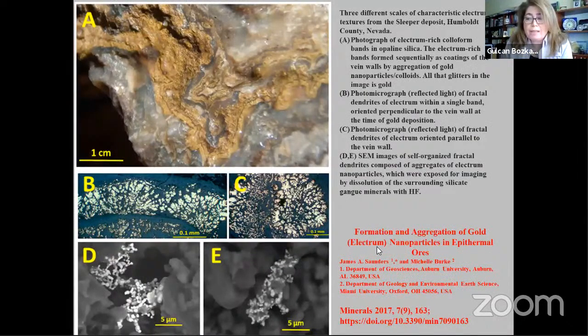It was the gold-rich bands that are present in many of the United States epithermal deposits that gave the idea of colloidal transport rather than direct precipitation from solution. Extremely gold-rich bands, as you can see, form at a variety of scales. And in the bottom two images, you can see the aggregation of the sub-micron colloidal particles, which are part of the way to forming the larger layers. What is not clear is whether the particles were transported at this scale or have formed from smaller ones.